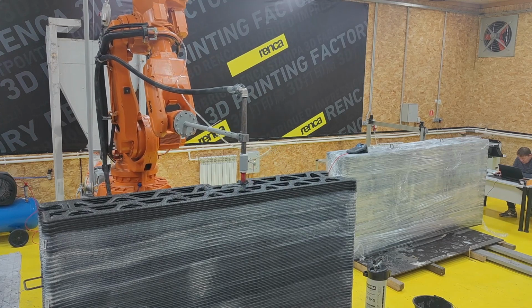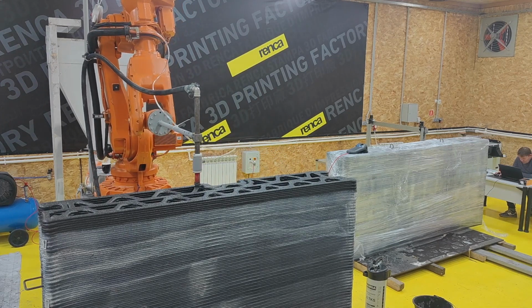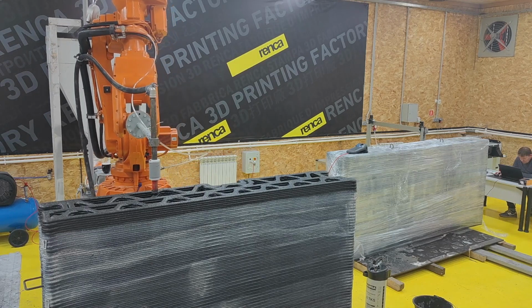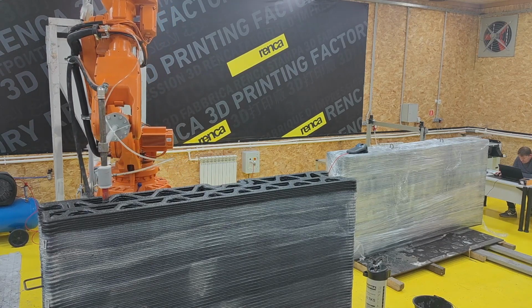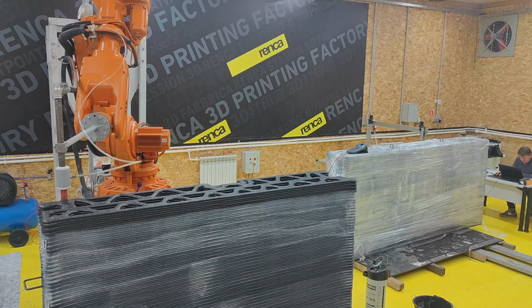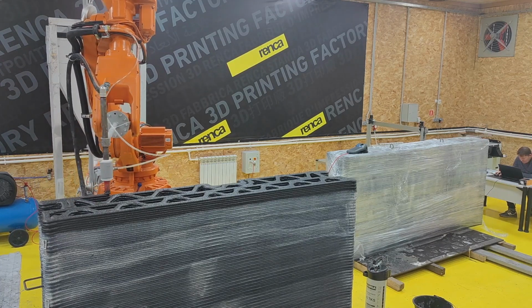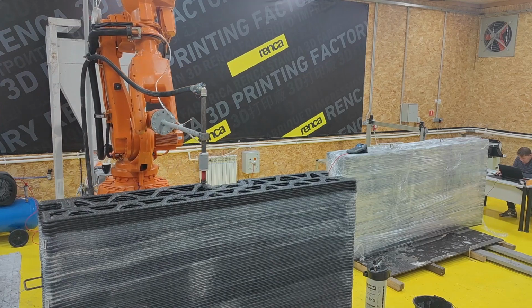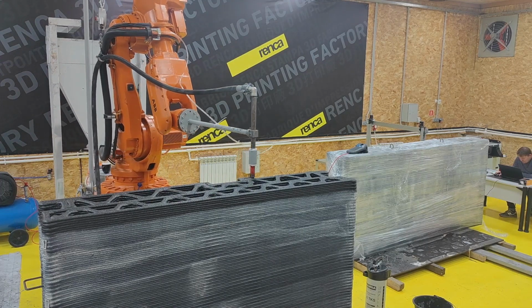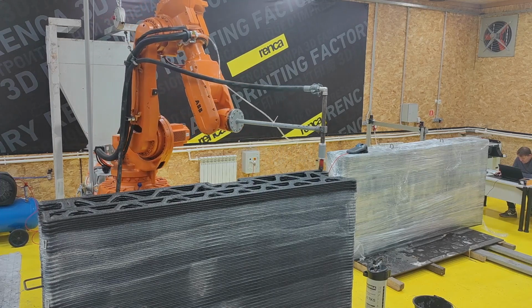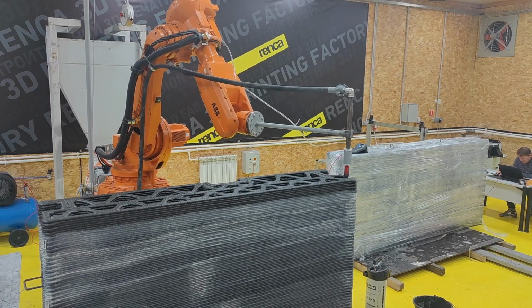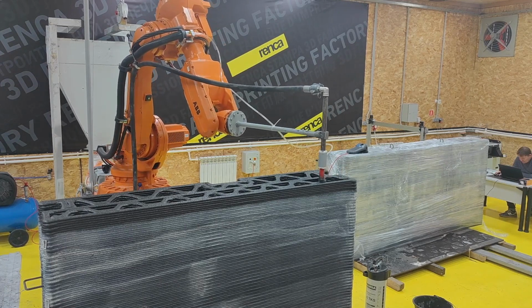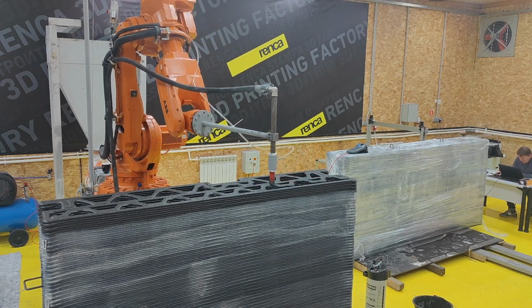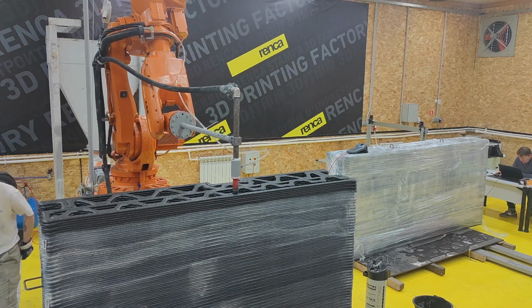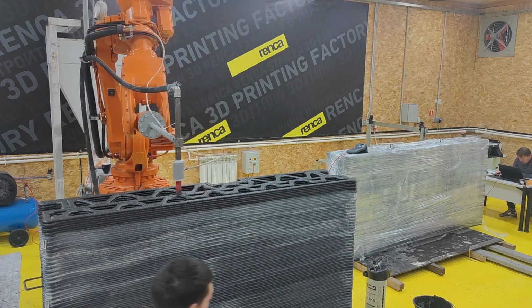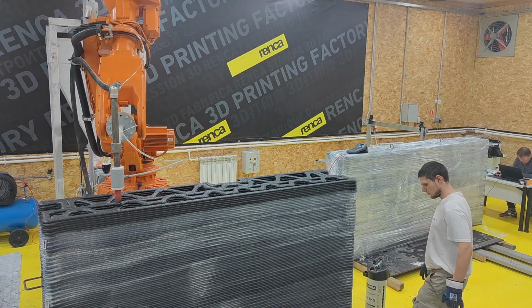Sticky isn't a word I've heard applied to 3D printed concrete. Is that unique to the geopolymer mix, kind of flowing through the hose if it's very hot? Sorry, can you repeat the question? When you're working with 3D printed concrete, when it's flowing through the hose, sometimes you get clogs in the hose if the aggregate's large, or if too much accelerant, something like that. Would the hose clog for similar reasons or different reasons with geopolymer? No, practically the same reasons as with Portland.